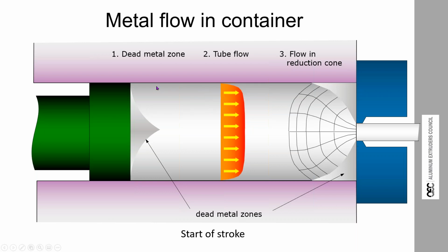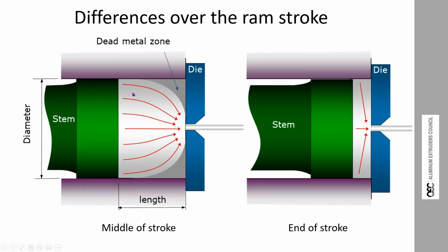But at the start of the push, the aluminum has a pretty relaxed way that it can create the reduction from, say, an 8-inch billet down to a 2-inch profile. This is the natural reduction cone. This forms. As we proceed, we get down to a point where the natural reduction cone is now bigger than the distance left in the billet. Now we start to force the way the reduction occurs. And this can lead to changes in the shape that's coming out. And this is where we can get front to back variation in our shapes.